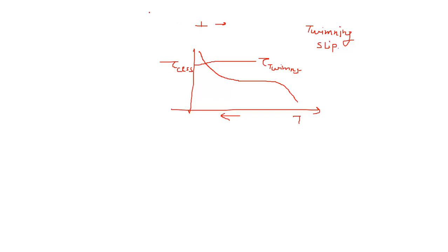So as you can see here, the room temperature will be somewhere here, T room temperature. So in some materials this crossover happens above room temperature, and in some materials this crossover happens below room temperature. In case of FCC this is the case, whereas in HCP, let's say in magnesium, you will find more twins in the microstructure. Because at room temperature also there are not many independent slip systems active, hence another mode of deformation is also taking place, which is basically twinning. Hence at room temperature slip occurs, but I am talking about low temperatures, cryogenic temperatures, not room temperature. I hope this is clear.